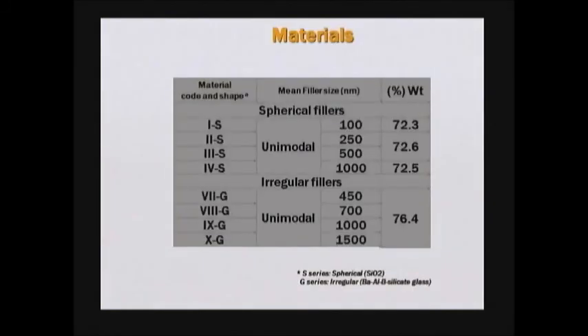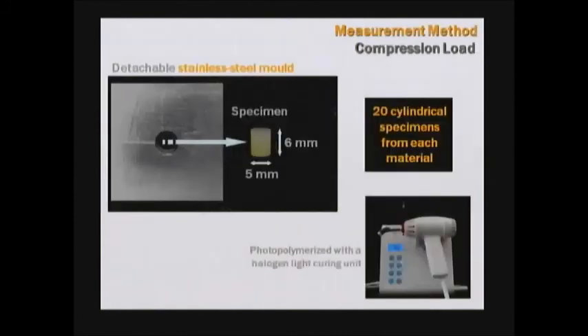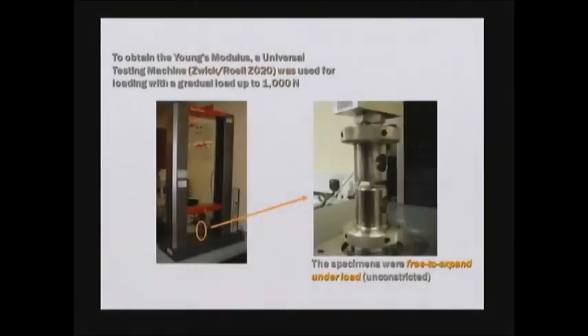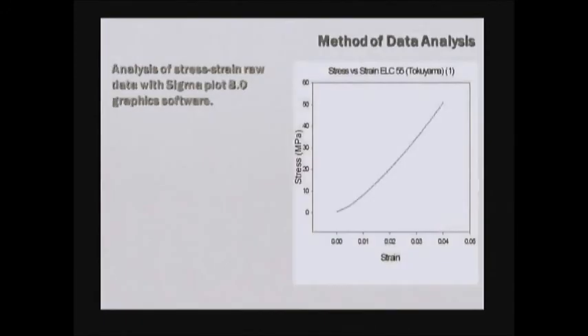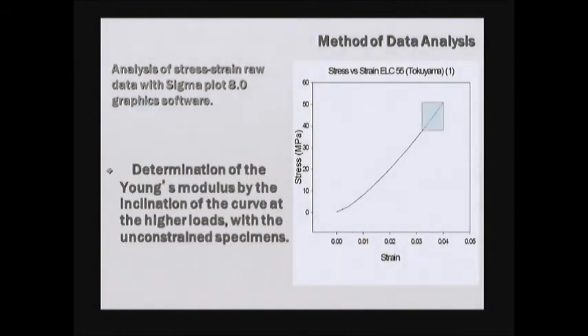You remember the big table, this is the one used for that one. This is the details of the specimens. This is for the Young's modulus, so some rod cylindrical specimens. They were placed there on a universal testing machine. They were free to expand, and they were loaded with a gradual load up to 1,000 newtons. This is the raw trace that we got, the strain stress curve, and by looking at this part here, we were able to determine the Young's modulus of those materials.